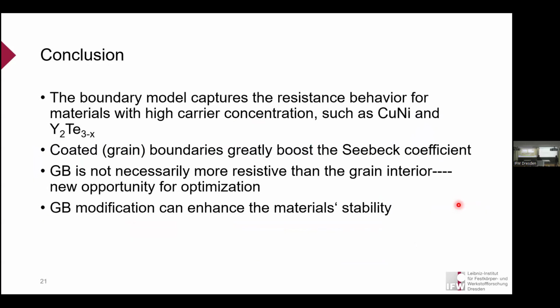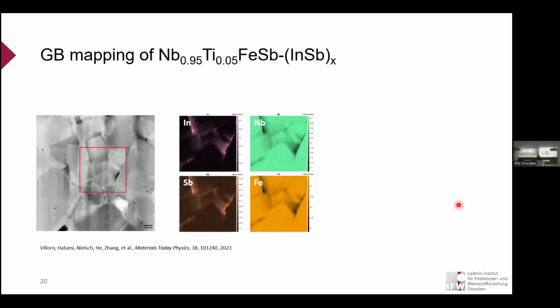Well, I didn't show the detailed microstructure here. I think the grain size is usually on the level of, let's say, 1 micron. The effective grain boundary depends on the doping level. With higher doping we have effectively larger grain boundaries, but typically it's in the range of, I would say, tens of nanometers. As for the mean-free path at room temperature, this discussion also involves a lot of the community, because usually the charge carrier has a much smaller effective mean-free path. So the question is whether this mean-free path picture is really valid for this material. I mean, it's valid, but maybe it's the grain boundary itself that makes the scattering particularly stronger. This is not something I can answer very well for now, but it's definitely a very interesting topic.